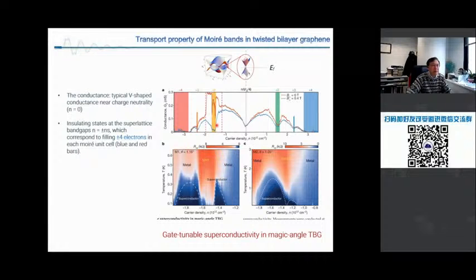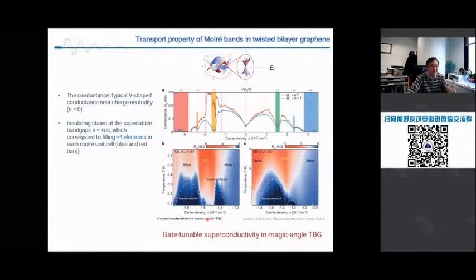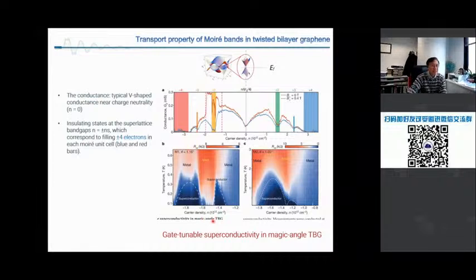Once you apply a magnetic field, then suddenly it changes. It breaks the superconductivity state. So this material is interesting. The superconductivity is gate tunable. Before, there was no report about such materials where you can use a gate electric method to tune the superconductivity and the insulating state. People call this a Mott state, but actually there is still debate whether this is an insulator or another phase, right? The superconductive phase.